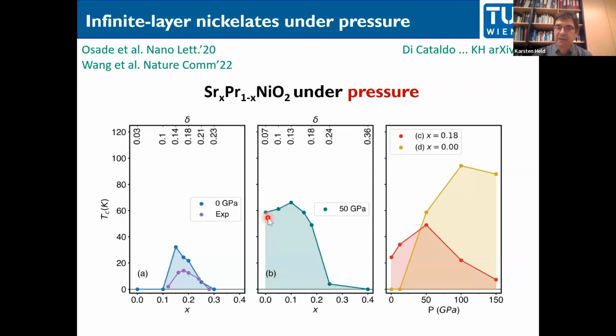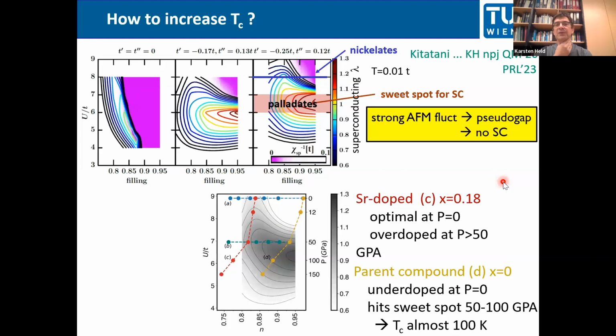So let's look at the parent compound. And that's the last curve I'd like to show you here. That is 0% doping, so it's a yellow curve. So it first increases to this value, and then further increases up to almost 100 Kelvin. So it's as good as the cuprates before decreasing again. So how can we make sense of these calculations?